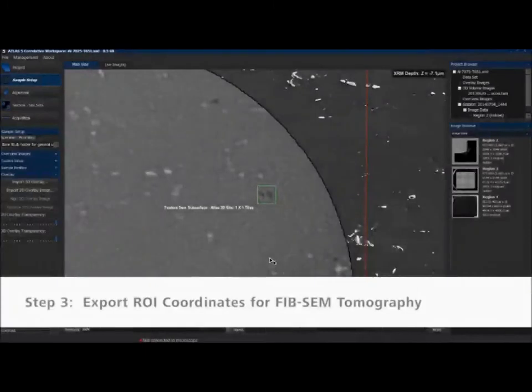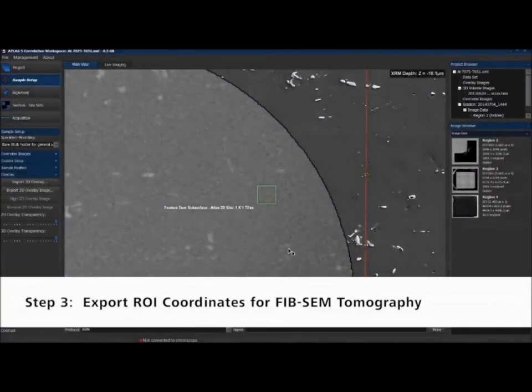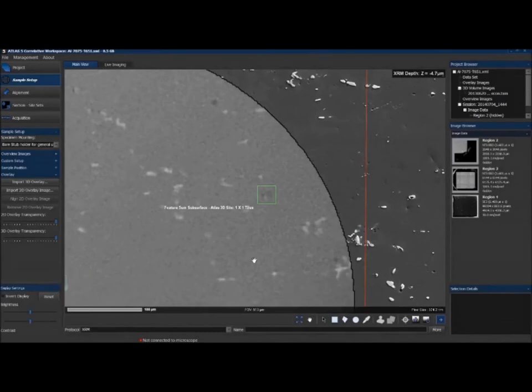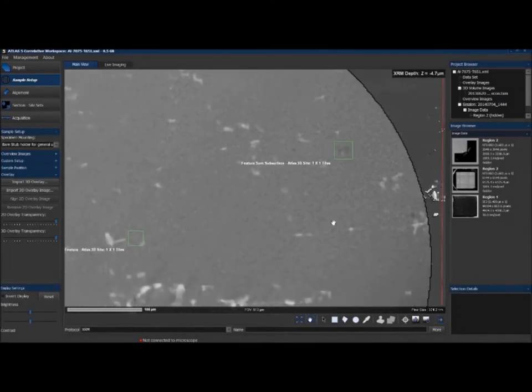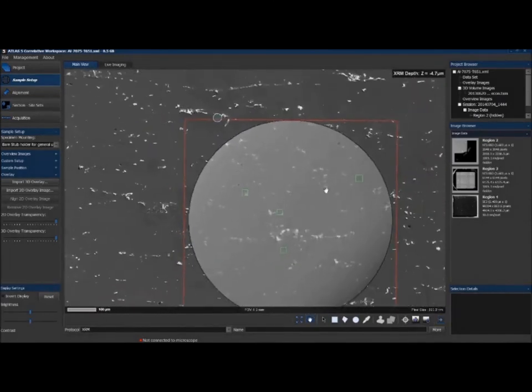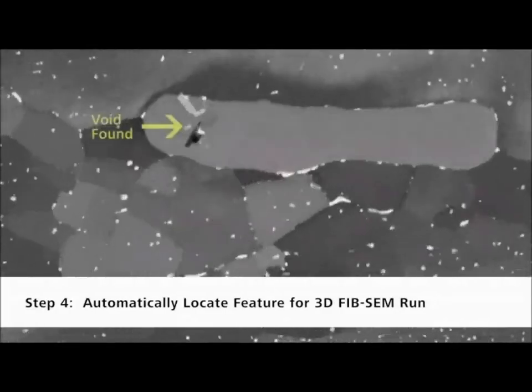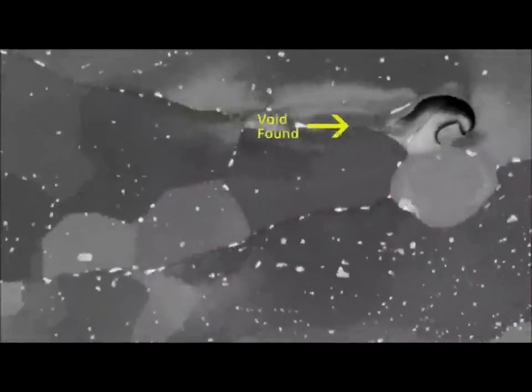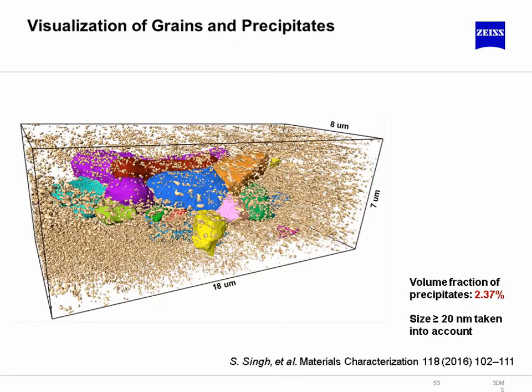You load in an X-ray data set here depicted in yellow. You then scroll down through the interface and have detected a void. So this black region in that green square is a void that I'd like to then inspect that is 10 microns below the surface. I otherwise would not have known that that feature is there. And now I can pick multiple regions and proceed with the automated 3D FibSem tomography. I've captured this inclusion and the void behind it as well. And so now I have a rich data set that I can quantify. And I'll skip forward just for the sake of time past the video and show you some of the results.